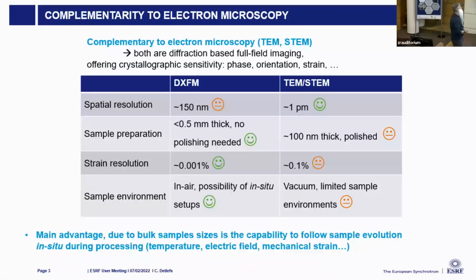So it's conceptually very similar to transmission electron microscopy. We have worse resolution, of course, but we have the huge advantage that we can work with much thicker samples, bulk-like samples that don't need to be specially treated. We can measure in transmission millimeter-sized pieces of aluminum or other metals and biominerals and things like that. We have much better strain resolution because our angular acceptance of the lens is much better, and the X-ray incident beam is much more highly collimated than the electron beam typically. And because it's hard X-rays, we can work in air, we can go through capillary sample environments and things like that.